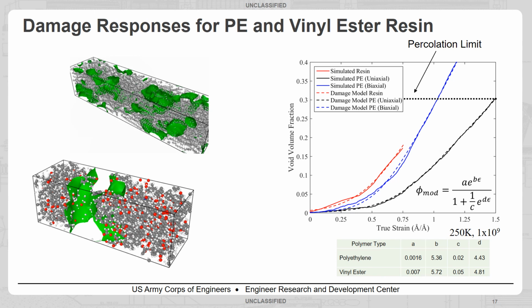So the black and blue curves here represent damage for polyethylene in uniaxial and biaxial tension. So we wanted to investigate stress triaxiality effects on the damage. So we see higher stress triaxialities cause increased damage, which is what we would expect. And then we look at the damage evolution of the vinyl ester resin here in the red curve. All the curves are able to be captured very well with our damage model.